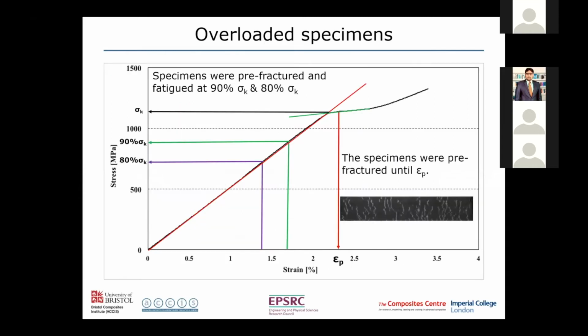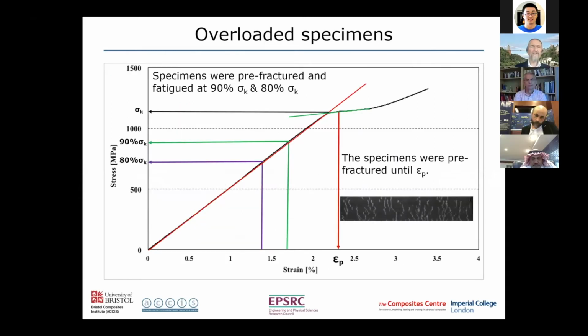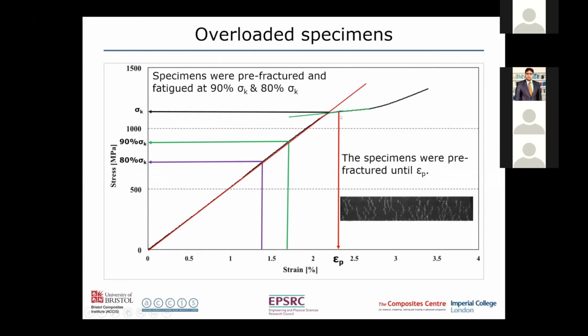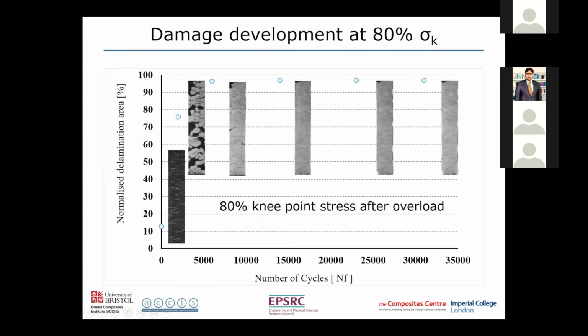We've also looked at loading it beyond this pseudo yield point. So initially we preload it up to this point. We go beyond that yield point, so introducing damage. So we've already got these fragmentation events that have occurred. We've got fragmentations in the specimen. And then after we've put that damage in, we fatigue it at some proportion of that knee point stress and see what happens. At 80% of the knee point stress, you see that the damage does spread after a few thousand cycles.